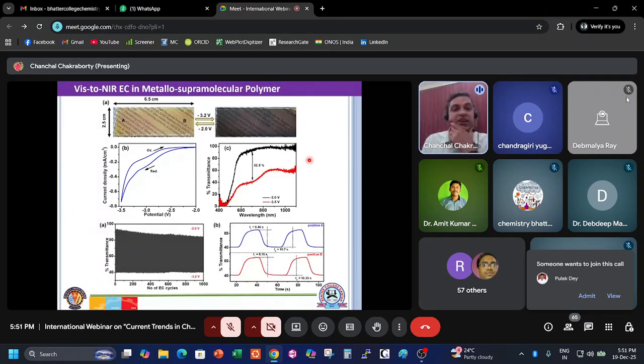So I'll show the visible to NIR electrochromic behavior of this material in the solid state device. Initially it is pale yellow in color, but when the cobalt center is reduced, it gives a brownish black color. This is associated with the reduction of the cobalt center to cobalt 1, and then there is a reversible oxidation from cobalt 1 to cobalt 2, associated with the transmittance change between the states. It is highly durable, and the coloration time is 8 seconds and the bleaching time is around 10.7 seconds. Coloration time means the time required for yellow to black, and black to yellow is the bleaching time. The important thing is solar irradiation blocking.